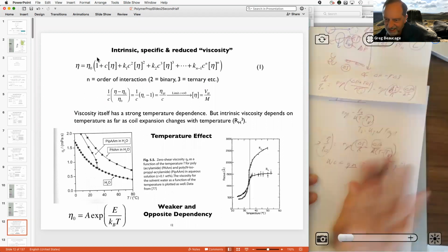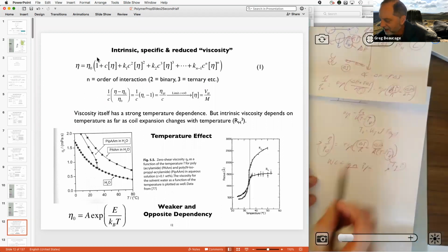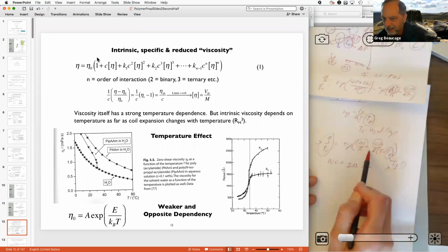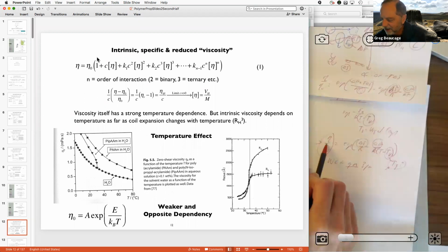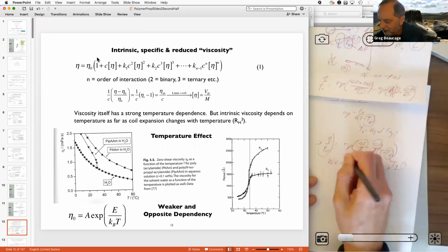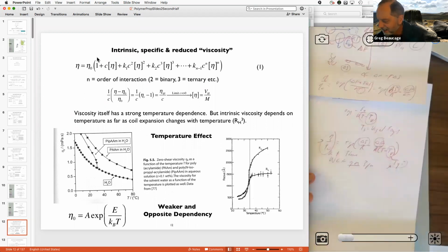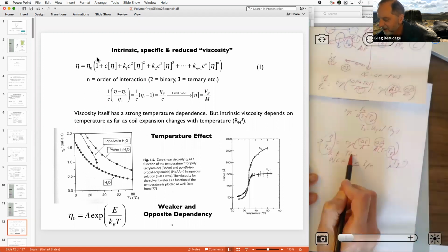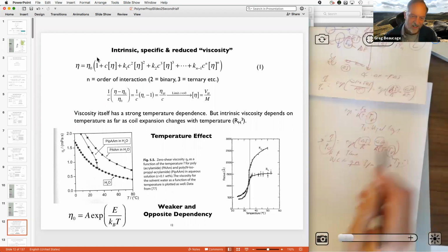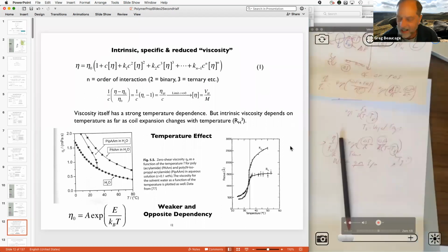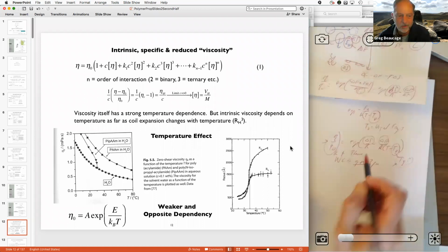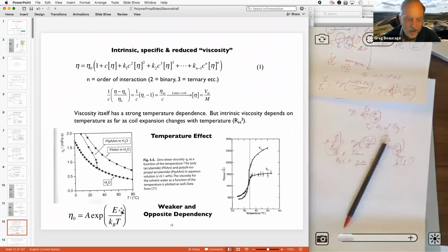So again, you're into the never land of associating thermodynamics with kinetics. Generally, thermo does not equal kinetics. You can't take kinetics and say thermal; the two are separate things. Basically, you can try to force fit it, and this will predict anything, but for most polymers, it's just a simple thermal dependence, like in Arrhenius, that should be negative here. And that'll work fine as long as you're far from the glass transition.